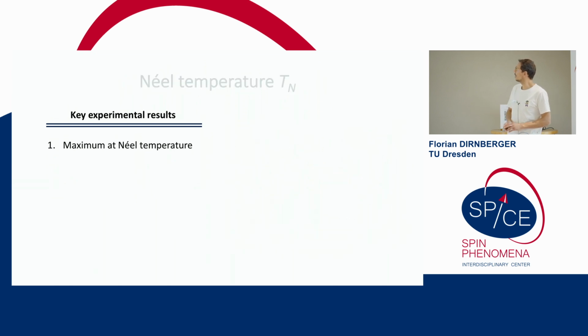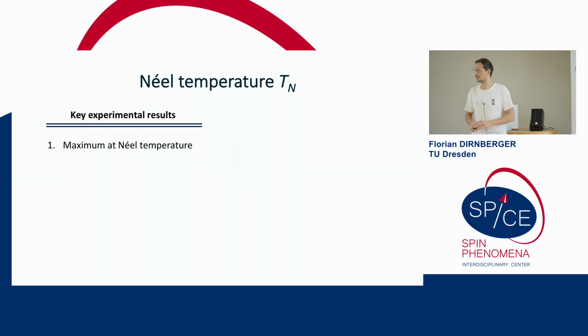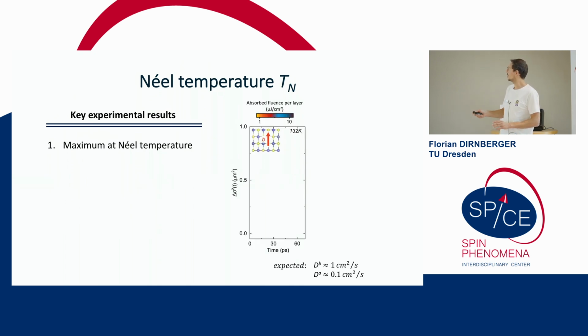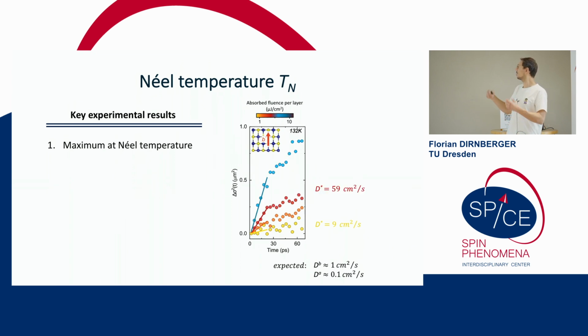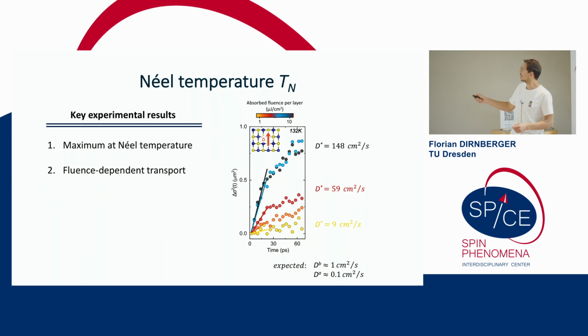So I'll show you some more results of exciton transport at this Néel temperature, particularly what happens when we look at the transport along the B direction of this crystal for different excitation fluences. When we start to increase the fluence, you can see here the solid line, or the slope of that line, that represents the diffusion coefficient. So when we increase the excitation fluence, the slope of that line increases, and it continues to increase as we apply more fluence. We get a higher effective diffusion coefficient. So the second key result is that the transport of excitons at the Néel temperature is fluence dependent. The more light we shine, the faster the excitons move away from the excitation region.